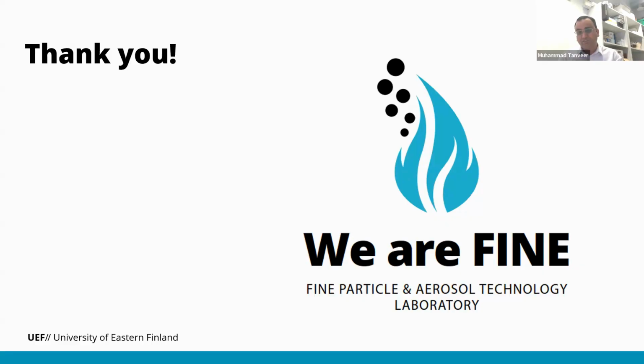It's good if we collect particles from very close to the flame, like evolution stages, in cases where homogeneous nucleation or heterogeneous nucleation is happening. So in our current study, we have done this. We have actually collected quite small particles, around 2 nanometer, very small particles. We're able to quench those particles from very close to the flame.